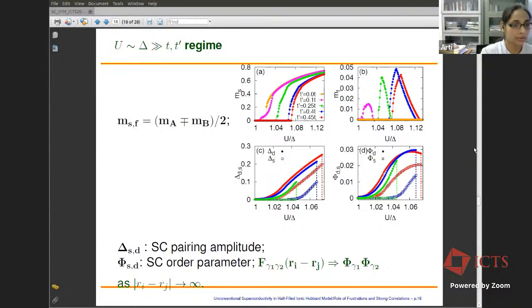So this basically shows that the frustration of the magnetic order is actually stabilizing the superconducting phase. You can see very clearly that the transition point at which the magnetic order sets in is also the point at which the superconducting order drops to zero. So only within the range of parameters where the system does not have any magnetic order, superconductivity survives. Then from the off-diagonal long range order correlation function, one can also calculate the superconducting order parameter. And what we see is that the superconducting order parameter for D wave and extended S wave is much smaller than the pairing amplitude, indicating the possibility of a pseudogap phase in this superconducting model.